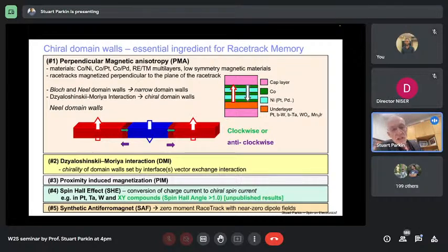And some of the most important ingredients are shown here. The anisotropies that can be induced by interfaces, something I didn't discuss, but typically it's an interface with a heavy metal layer like platinum, palladium, tungsten. You get something called a Dzyaloshinskii-Moriya interaction that causes the magnetic moments in the layer above to want to be perpendicularly oriented in a chiral manner. This is a very interesting point, and this means in this cartoon, you can see the red moment pointing up, and then the blue moment pointing down.